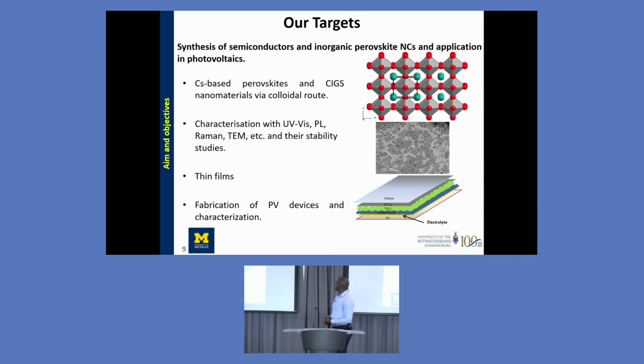So our main target is to synthesize inorganic perovskites and semiconducting nanocrystals. And with the synthesis, we're targeting the preparation of cesium-based perovskites. For the cesium-based perovskite, here I wanted to show you the structure of perovskite. This is a three-dimensional perovskite. It's structured like this so that one can prepare the crystals and have a good arrangement. Such an arrangement will allow the flow of electrons through any layer or any film that one will want to prepare later on. Ideally, you have a cubic structure with all the atoms constituting the perovskite, but some of those atoms share bonds with atoms from another cube, thus making the three-dimensional structure.